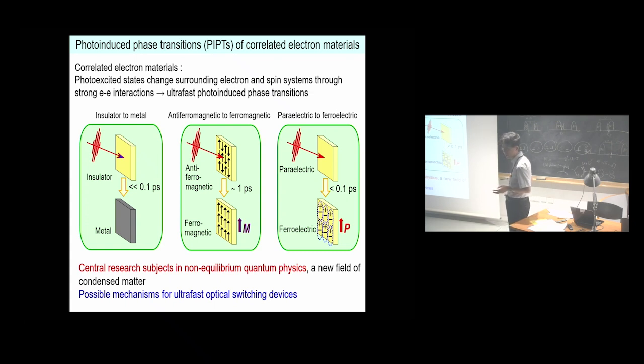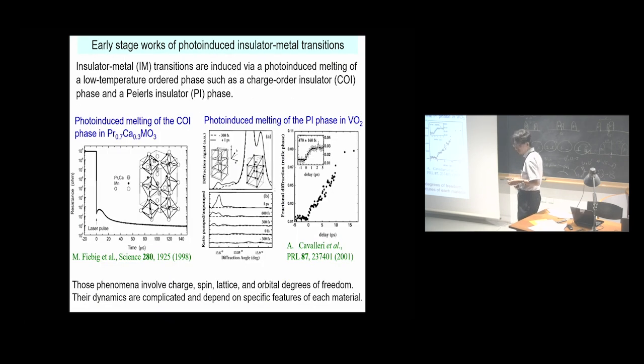This insulator to metal transition is the most typical photoinduced transition in correlated electron materials. As early stage works of photoinduced insulator metal transitions, the studies of perovskite manganite and VO2 are well known. In those materials, insulator metal transitions are induced via photoinduced melting of low temperature ordered phases, such as the charge order insulator phase in manganite and the Peierls insulator phase in VO2. So far, various phenomena have been discovered along this strategy. Those phenomena involve charge, spin, lattice, and orbital degrees of freedom, so they are very interesting. But their dynamics are sometimes complicated and depend on specific features of each material.